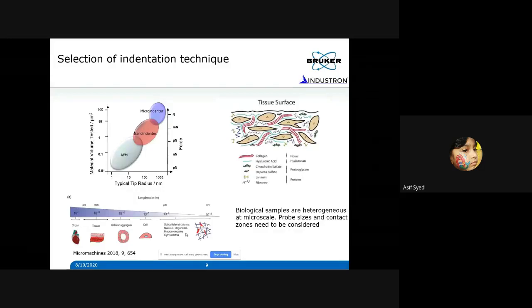But all these techniques depend upon the length scale that you want to work with, right? For example, the micro indentation, people may be familiar with optical based micro indenter, where you do the same experiments but use an optical microscope to see the indent size and measure the hardness. It can go up to a certain length scale, but beyond that you cannot go because you cannot see those indents in optical, because optics doesn't have the resolution. Then you have this Nanoindenter, which can extend this to hundreds of nanometers or less than 100 nanometers in dimensions. Okay, but if you want to go to sub nanometers or the single nanometer, you need something like AFM.